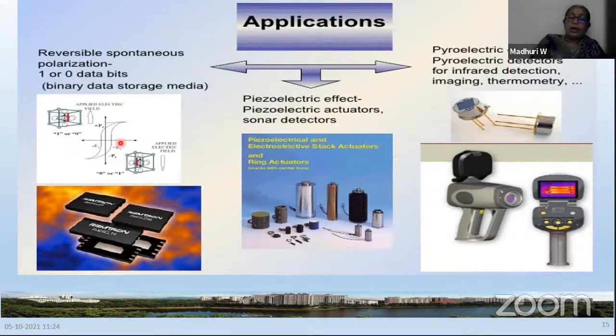So if you are applying an AC field, continuously, with the frequency of the AC field, it gets polarized. Fine. You're polarizing and depolarizing your ferroelectric or your piezoelectric. So when you polarize, you take the data point as 1, then you depolarize, your data point will be 0. And that's how, in the binary system, you can always store your data on piezoelectric materials.